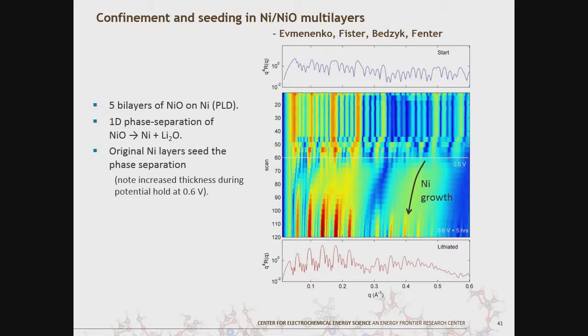Something that's currently going on is work that Gena Evmenenko and Mike Bedzyk have been leading, looking at nickel oxide, which is a classic conversion material, in both film and multi-layer forms. Just like before, this is a block of X-ray reflectivity data as a function of time, and you can see these Bragg peaks show up as the bright colors.